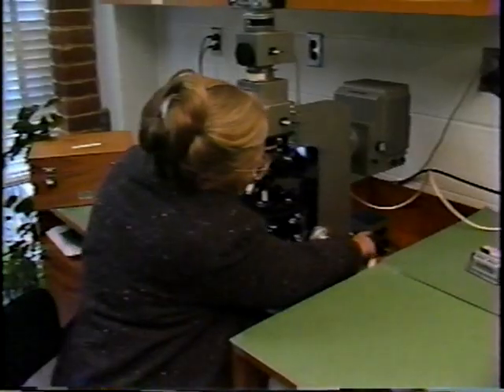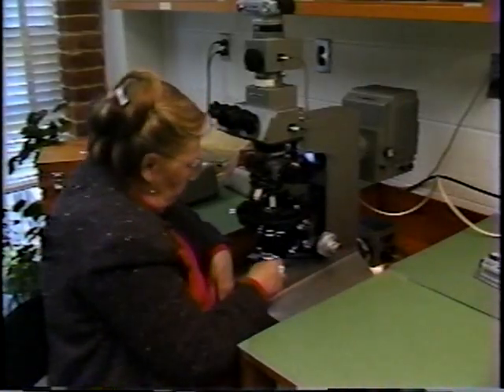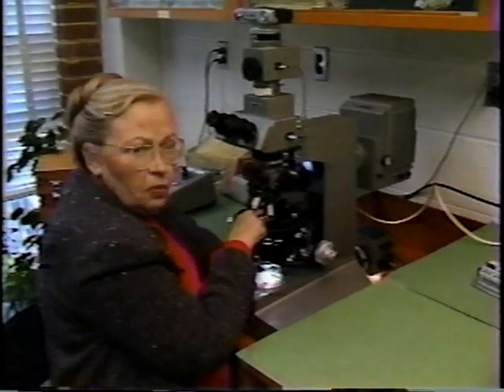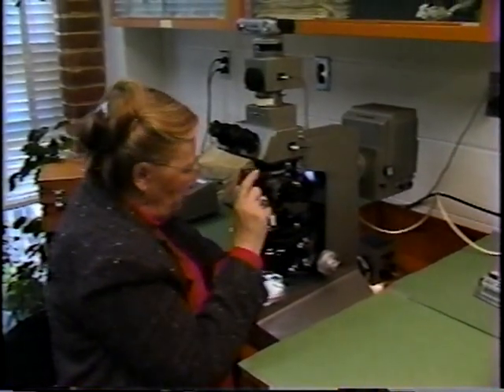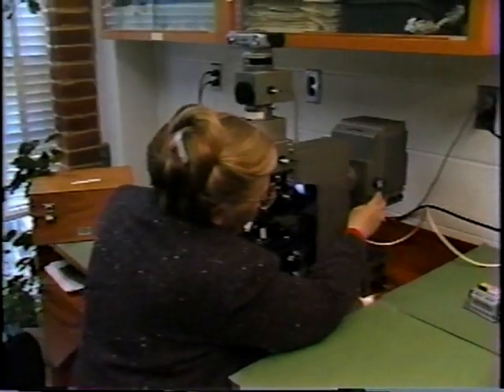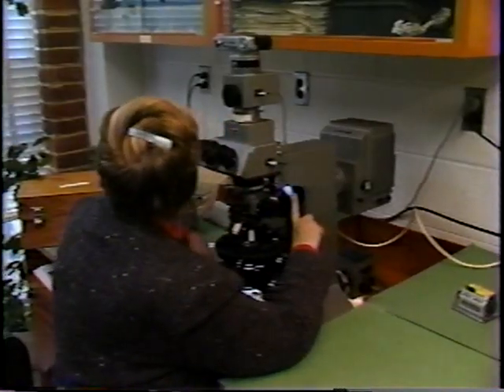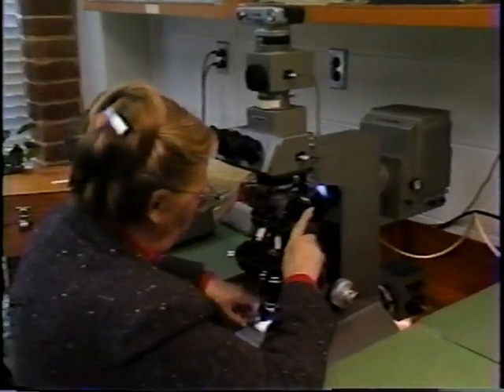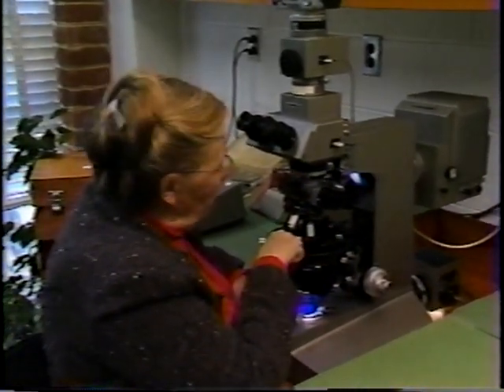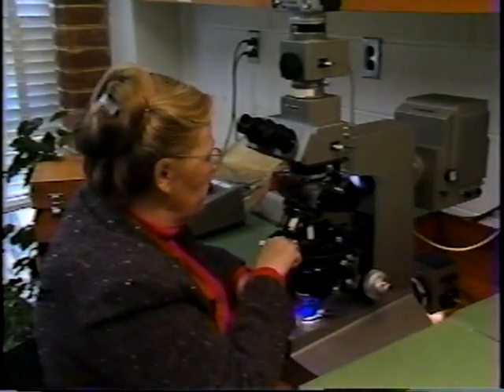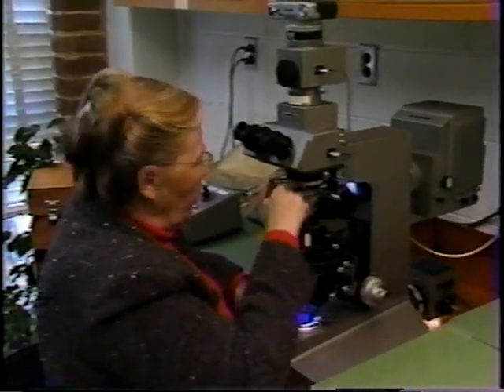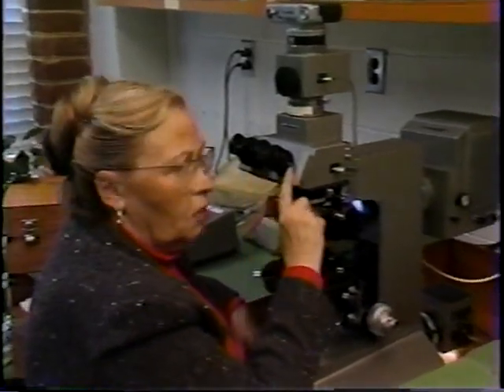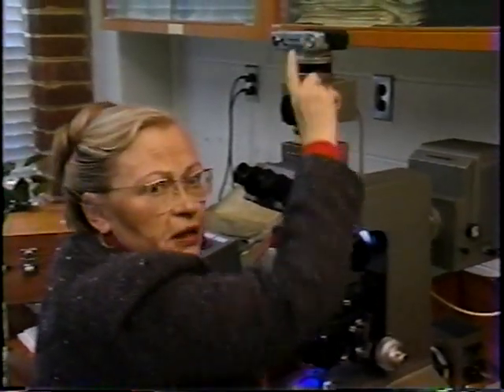When we need to study the very fine microstructure in Portland cement concrete, we use this microscope. This is a fairly special microscope. It has two distinct forms of illumination. First, white light is produced in this housing back here and goes through the base of the microscope, comes up through the condenser to the specimen, where white light can be studied with all the features of an ordinary polarizing microscope. Secondly, we have ultraviolet light produced in this housing back here, coming through this collimating system to a little half-surface mirror in here, where it comes down to the specimen, creates fluorescence within the specimen where the epoxy has accumulated in voids and other structures, comes up, can be seen with the eyepiece, or if desired, the light can be sent up to the camera so we can take pictures.